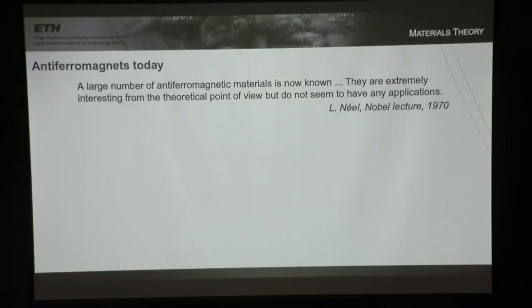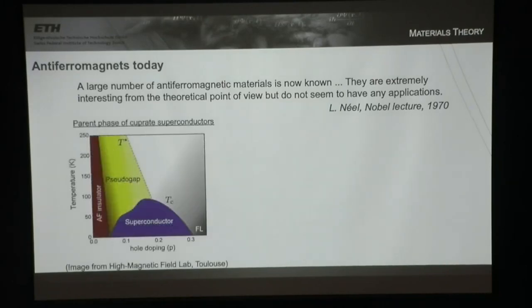And so I want to give you two examples, because I'm actually going to loop back to both of these later. The first, this is an image from the High Magnetic Field Lab, or a cartoon, of the phase diagram of the cuprate superconductors, the high temperature superconductors. And so this is temperature as a function of doping, of the number of carriers. And this is the superconducting dome that we're normally interested in. So I dope this many carriers, and I get superconductivity up to around 100 Kelvin.